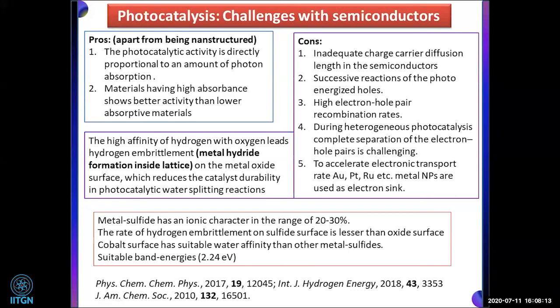So out of all these five, the main difficulty is the high electron-hole pair recombination. And one more point I want to add here. I think in the previous session also, somebody asked about the usefulness of metal oxide versus the sulfide in case of photocatalysis. If you read the line, the high affinity of hydrogen with oxygen leads to hydrogen embrittlement, that is metal hydride formation inside the lattice on the metal oxide surface, which reduces the catalyst durability in the photocatalytic water splitting reaction. So this is actually what we found.